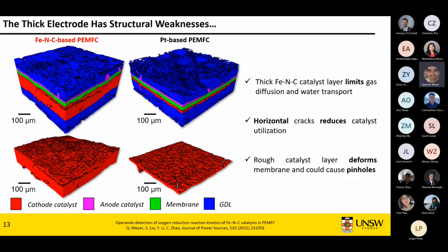You can see here we've got some weird cracks in the electrode thickness. This is typically not what you want to have, because that means that as the material dried, it basically solidified and cracked. And then when you deposit the next layer, the materials won't actually stick well onto each other. This will create flooding, will create low contact, will basically make a lot of your catalyst electro-inactive. At the same time, if you look at platinum, it's quite the opposite. It's a very thin, very uniform material. You have cracks through the material, which are excellent for gas diffusion. Completely opposite of the kind of cracks you've got in the catalyst layer.